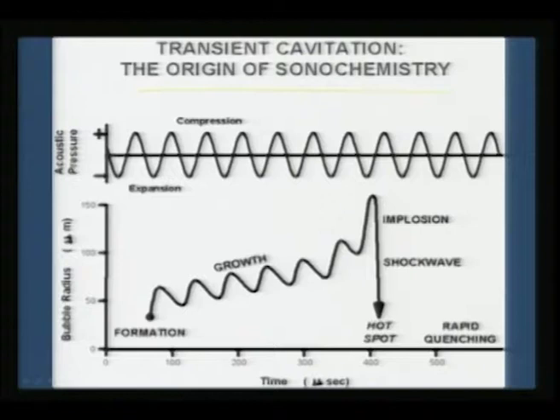So, as I told in the previous slide, we have the formation of a cavity, and this cavity grows in size over several cycles due to the compression and expansion wave. If you see the y axis, you see the bubble radius. Typically from the 20 micron range it grows up to nearly 150. Now, when it has gone through several cycles, there is a particular cycle at which in a single step it will grow to this maxima, and this is the